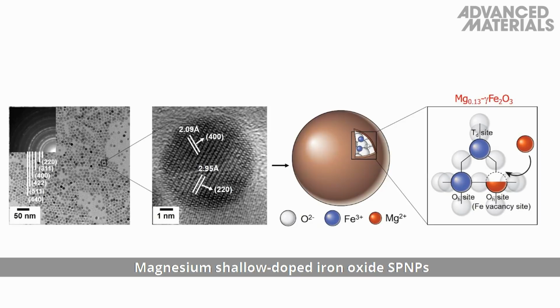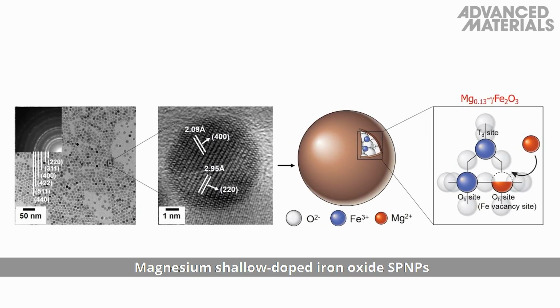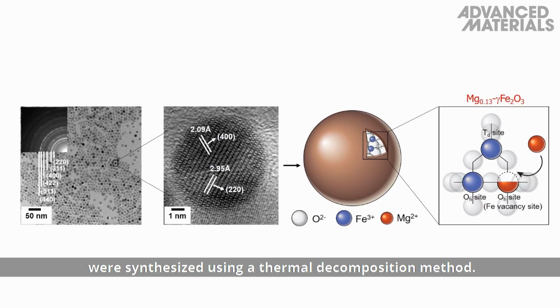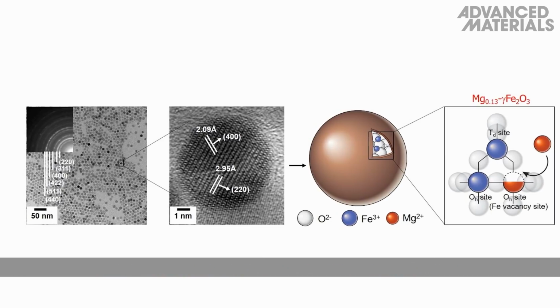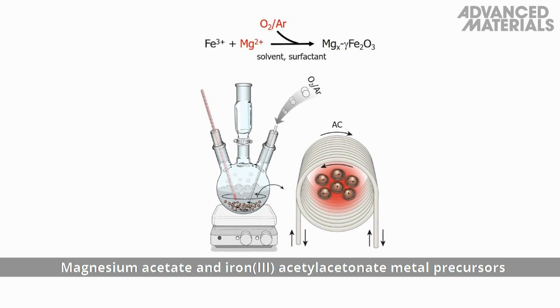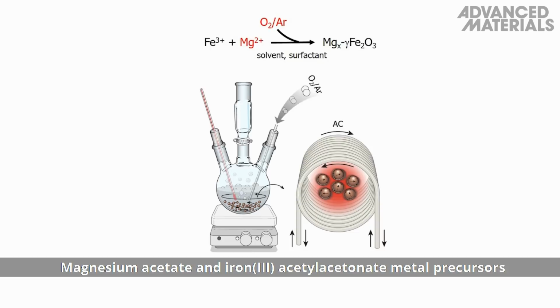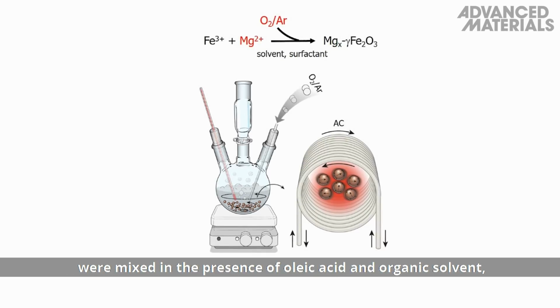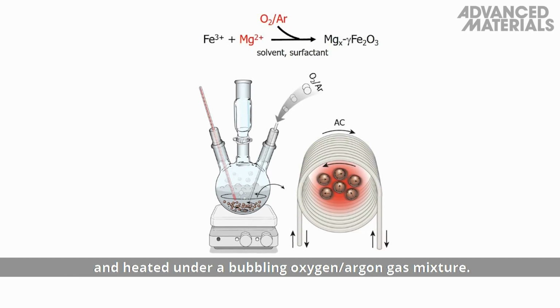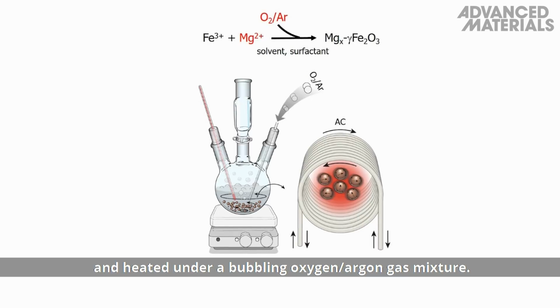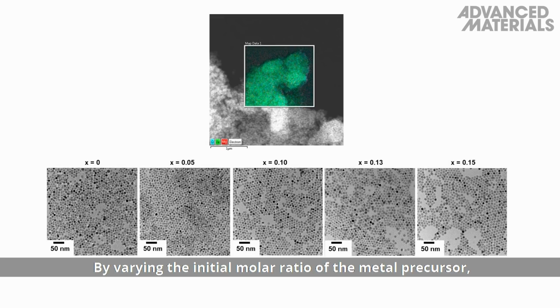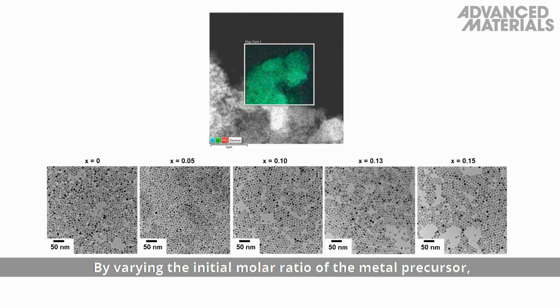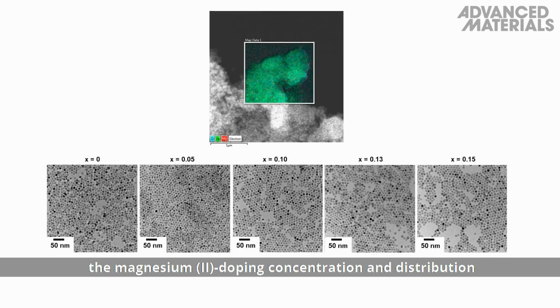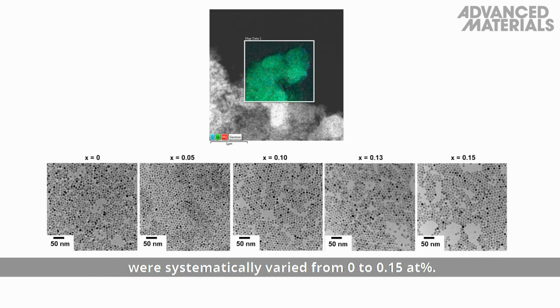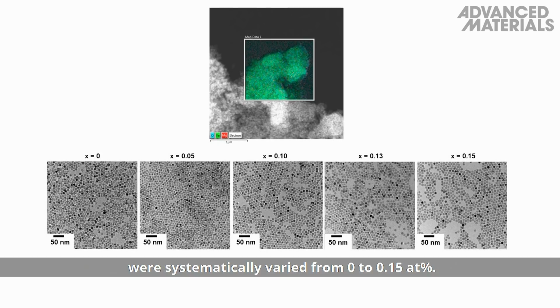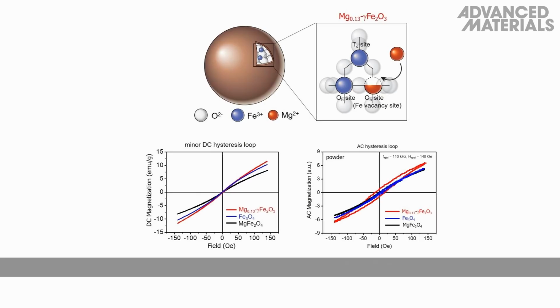Magnesium shallow-doped iron oxide superparamagnetic nanoparticles were synthesized using a thermal decomposition method. Magnesium acetate and iron(III) acetylacetonate metal precursors were mixed in the presence of oleic acid and organic solvent and heated under a bubbling oxygen-argon gas mixture. By varying the initial molar ratio of the metal precursors, the magnesium(II) doping concentration and distribution were systematically varied from 0 to 0.15 atom percent.